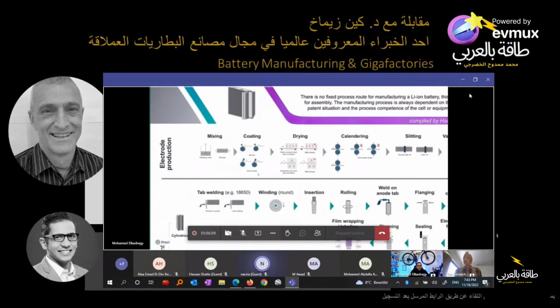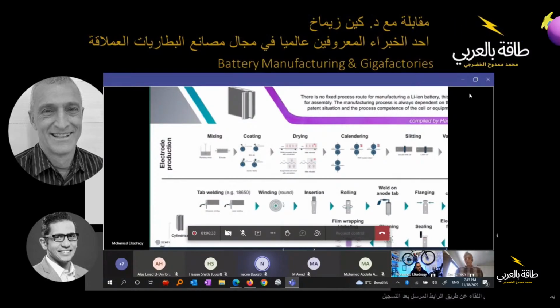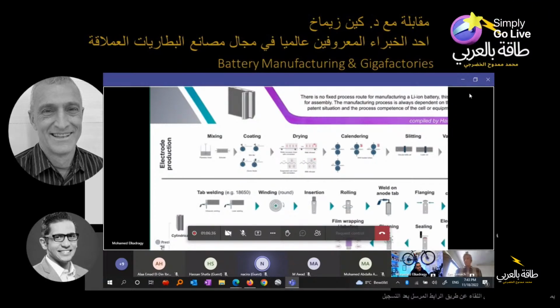Because remember, for instance, the CMC is really good at binding the graphite to the graphite, but the SBR is good at binding all of that to the copper electrode. And if you mix them in the wrong order, it doesn't work as well. Your tests will come out the same. Your viscosity tests will be the same. It looks the same. It's a big, dark, black, gooey liquid mix. But when you get to the end cell, the performance is totally different because you mixed it in a different order. And you're going to say why.